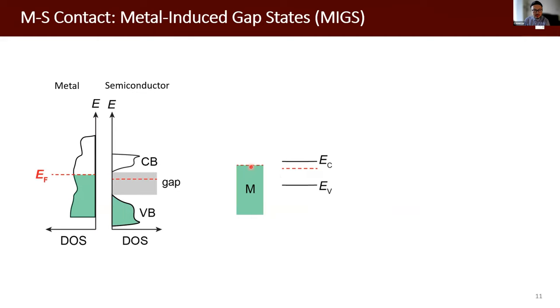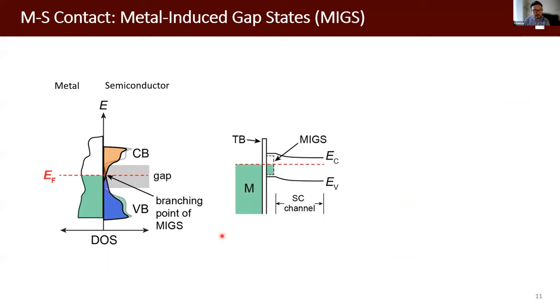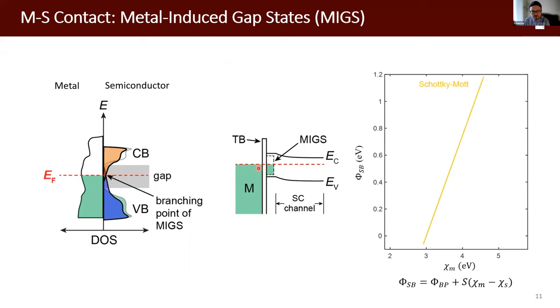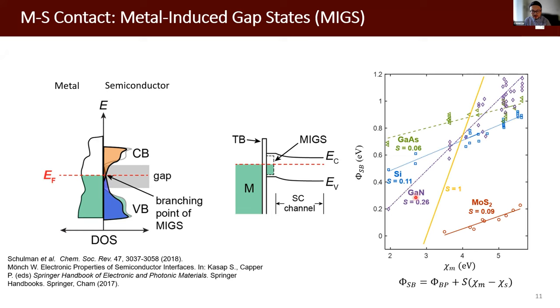But in reality, besides the charge transfer, there is also rehybridization of electronic states at the interface. As a result, there are additional electronic states introduced within the band gap on the semiconductor side. We call them metal-induced gap states. Some of the states originally come from the conduction band, some of them from the valence band. So in thermal equilibrium, the final Fermi level would be located around the charge neutrality point of these metal-induced gap states, which would lead to a large barrier height at the interface. If we update this plot with realistic experimental results for all different 3D and 2D semiconductors, the slope is always much lower than one. That means the Schottky barrier height cannot be effectively modulated by simply changing the metal work function.